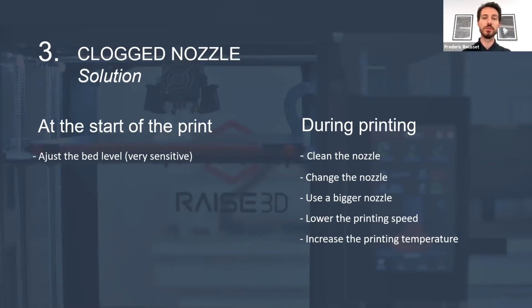If it is during the printing, you must clear your nozzle. This is the first thing to do. If it isn't working, you can change your nozzle and take a bigger nozzle that will reduce the pressure inside your printer, so it won't clog as much. If you still have some problems, you can try to tweak the different parameters that we have. The two that I would recommend are to lower the printing speed or increase the printing temperature.